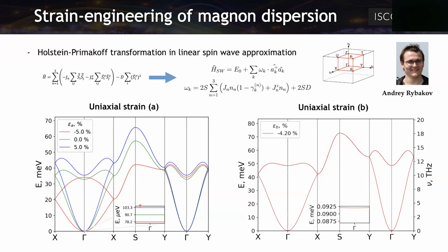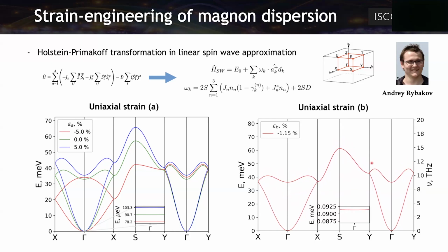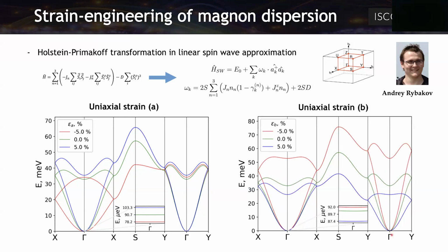When we are applying strain along B, in this case along the B axis, we have the opposite. Now we are expanding the material and this is decreasing, and we are affecting mostly this gamma-Y direction, and the dispersion is being decreased when we are expanding the material. So we have the opposite behavior. In this case, the compression is what is making these waves travel faster along this direction. And this can be observed also as the opposite trend. The colors are now inverted for the magnon gap here around gamma.